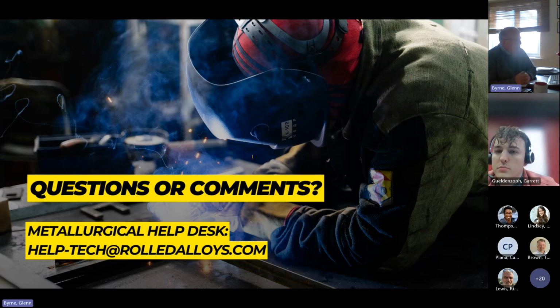Generally, people don't test anything less than 6 millimeter thick, and effectively, the point is you're trying to pick sigma phase up with this. You're not trying to establish some brittle fracture criteria. It's not a leak before break test that we're applying in these particular cases and numbers. So I think 6 millimeter is a decent cutoff. At that thickness, it's relatively thin. It cools quickly, and it's not so thick that brittle fracture becomes a problem. So I'd stick with the 6 millimeters that the international standards normally apply.